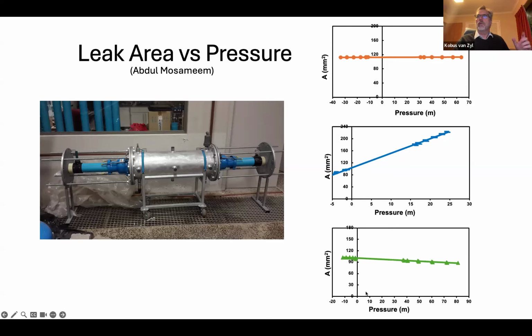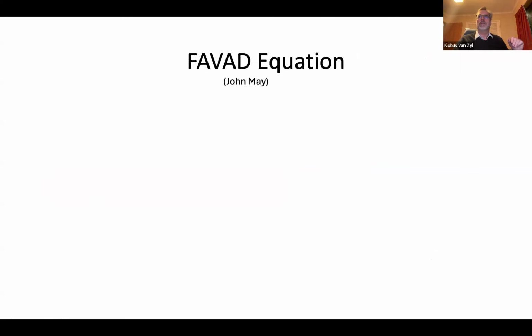The green there is circumferential cracks. They slightly decrease in area, but depending on different conditions, they can also increase. And what you see is that they're all linear functions of pressure. This equipment there was to look at what happens under negative pressure. So we increase the pressure on the outside of the pipe. And what you see on these curves is that when we go to negative pressure, the area line actually continues. So a longitudinal crack will open with increasing pressure, but if you have a negative pressure, it will decrease the area of that crack. And we understand this process quite well. We can predict for a given pipe what the slope of the line will be.